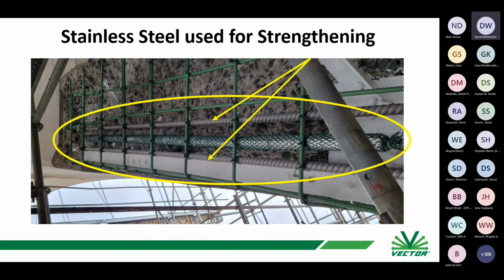Okay, you're going to see a couple places out there. I know one on span 2 when we do the walk around, where you'll see this kind of detail where they've had a certain amount of corrosion of the existing Melan steel. They're putting in supplemental reinforcing. This is for structural reinforcing, and they're using stainless steel rebar for that. And so you'll be able to see that on at least a couple of the repairs that are open and getting ready to go back in for the repairs.